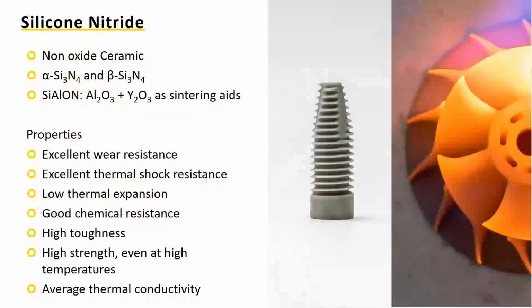The last material that I have for you today is silicon nitride. It's also a non-oxide ceramic. It's a mixture of alpha and beta silicon nitride, and our silicon nitride, as most silicon nitrides, is liquid phase sintered, which means it uses sintering aids of aluminum oxide and yttrium oxide. Silicon nitride has a few very outstanding properties, even in the ceramic world. For example, the excellent thermal shock resistance, while also having a low thermal expansion. You can work this material at high temperatures as you could at room temperature.